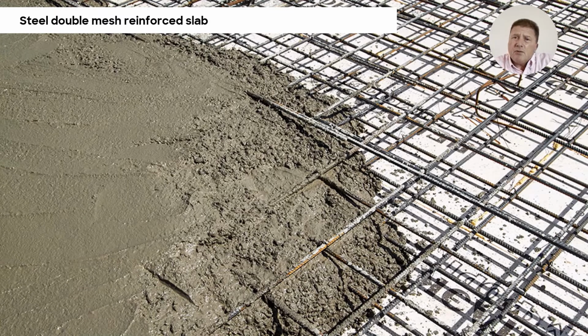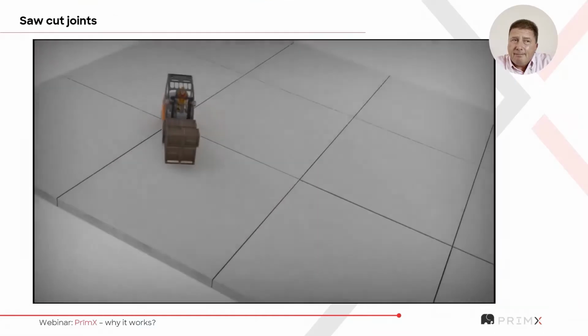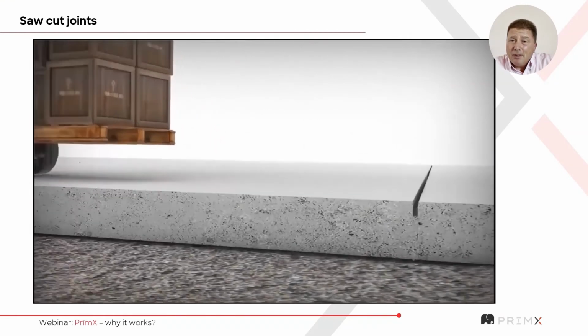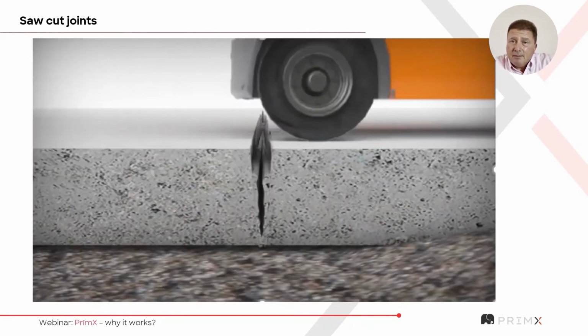Okay, so what do the saw cuts do? Well, the saw cuts relieve the shrinkage stress where we put them. In other words, we're forcing a crack to occur where we want it to occur. Okay, is there a problem with that? Well, in many cases, no, not really. But actually, in distribution centres, that's quite a significant problem because these are subject to high traffic intensity. And those forklift wheels, they're not softened in any way, shape or form. They're normally quite hard, quite durable. And as they rattle over a joint, a saw cut induced joint, they'll set up a bit of a shock wave, which in time will result in arris damage and the breakdown of the slab. Okay.